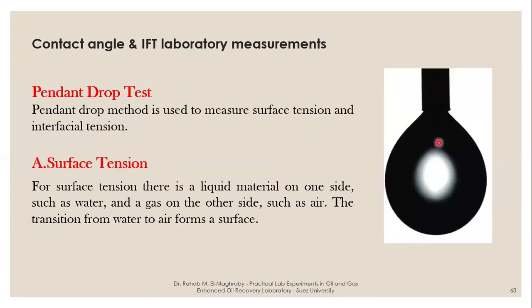For the interfacial tension, we use the pendant drop test. The pendant drop test is placing the drops, and according to where you are placing it, if it is in air, it's called surface tension. If you are placing it in another liquid, so oil in water, it's called interfacial tension. So a water drop or an oil drop, surrounded by air, surrounded by CO2, surrounded by nitrogen. In this case, it's surface tension, and it's called the pendant drop. And you can calculate the surface tension for this drop.